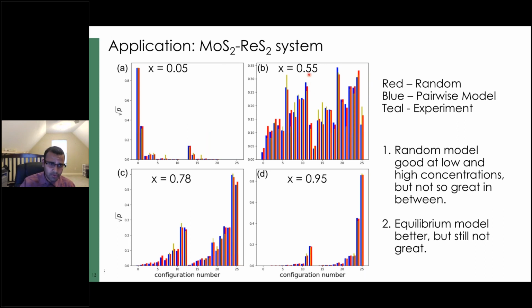However, if we look at intermediate concentrations, particularly the 55% and the 78%, you can see that, for example, the teal is distinct from both models, both the random model and the pairwise model. So what this is telling us is that the models are not doing a good job, at least the pairwise model is not doing a great job of actually replicating what we're seeing in experiments.